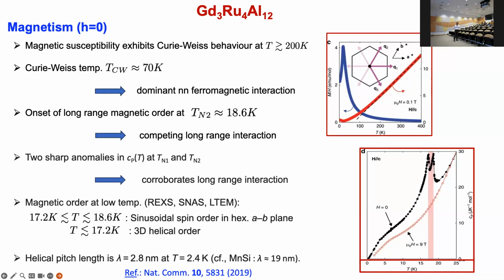Indeed, in the specific heat measurements, you observe two sharp anomalies at 17.2 Kelvin and 18.6 Kelvin. And based on real space spin imaging with resonant X-ray scattering, small angle neutron scattering, and Lorentz TEM, people have found that when you cool down the temperature, first there is an onset of sinusoidal spin order in the hexagonal ab plane. So you form some magnetic ordering in the plane, and at a slightly lower temperature, there is an onset of 3D helical order.